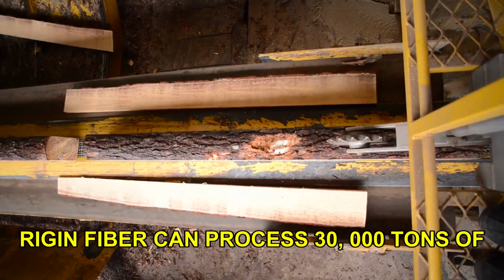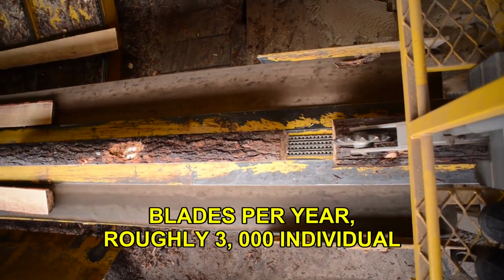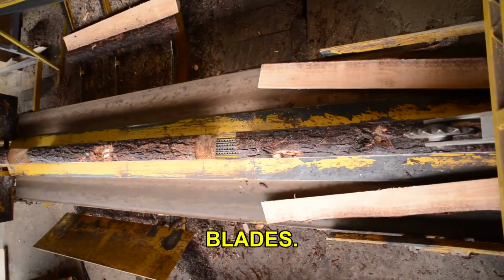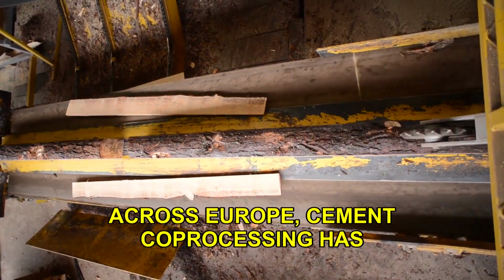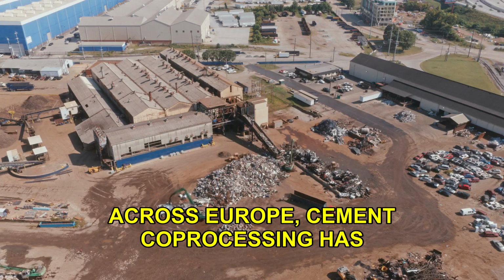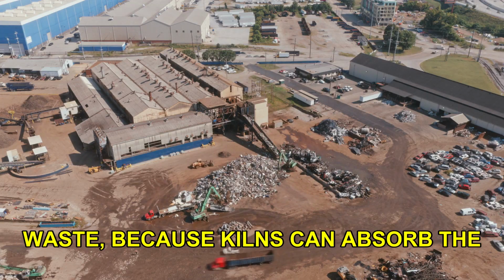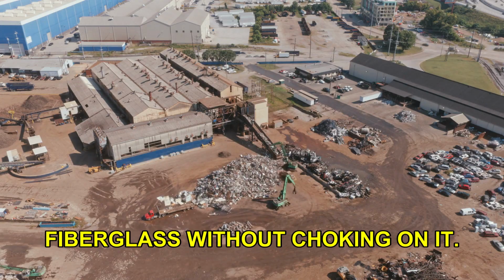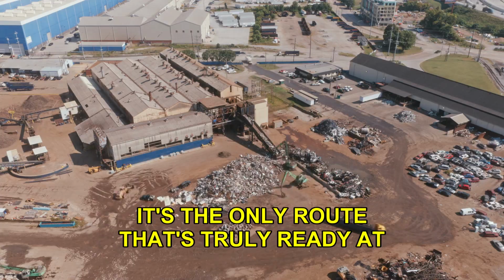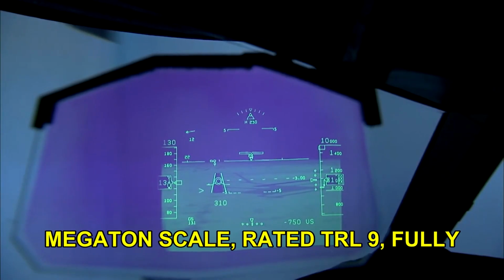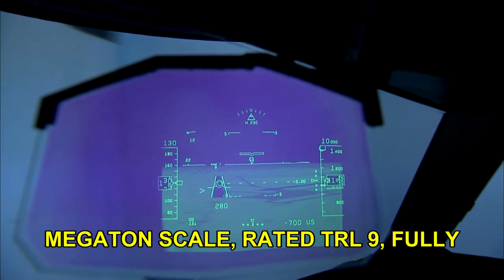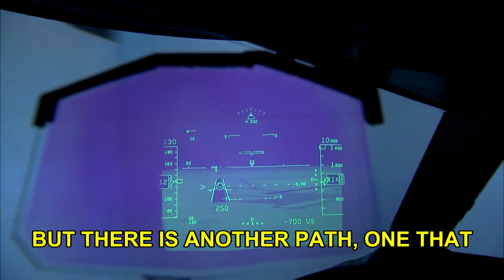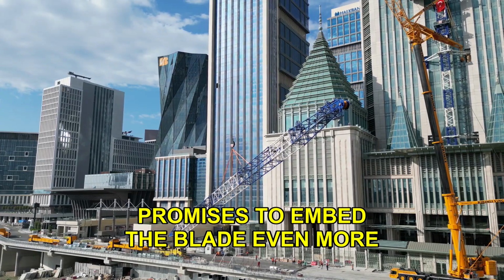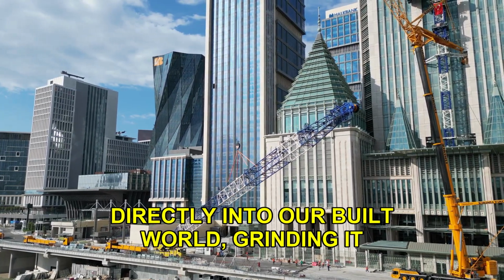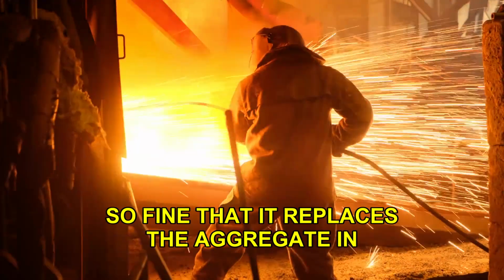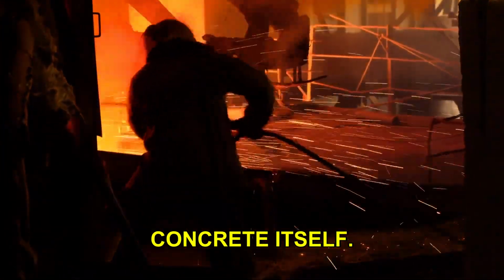Rigin Fiber can process 30,000 tons of blades per year, roughly 3,000 individual blades. And they're not alone. Across Europe, cement co-processing has become the default destiny for blade waste, because kilns can absorb the fiberglass without choking on it. It's the only route that's truly ready at megaton scale, rated TRL 9, fully commercial. But there is another path, one that promises to embed the blade even more directly into our built world, grinding it so fine that it replaces the aggregate in concrete itself.